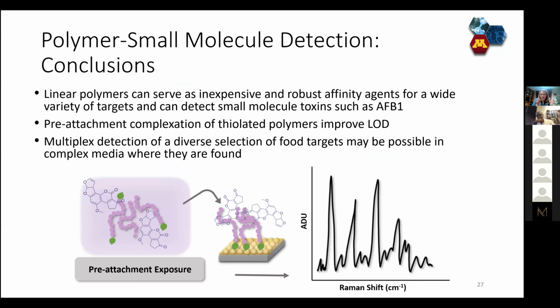So some conclusions from this little part before I show you the next part of the research, just to make sure we're all on the same page. These linear polymers do have good potential as affinity agents. There's lots of good reasons to use polymers. Both antibodies and aptamers are biomolecules that require sensitive conditions, and so linear polymers are much more robust in that way. We found that allowing the polymer to interact with the target ahead of putting it on the surface gave us a better limit of detection, and that using the thiol instead of the trithiocarbonate gave us better results.